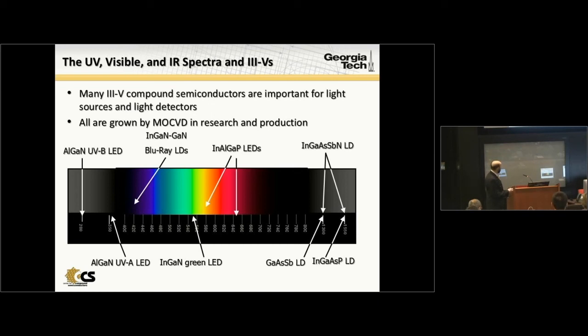However, other photon sources are important. I'm showing these infrared ones here, deep infrared ones, around 1.3 to 1.55. This is the technology used in optical fibers. I mentioned the 1.3, 1.5 micron fibers, 1.4 micron sources are this indium gallium arsenide phosphide quaternary grown by MOCVD.